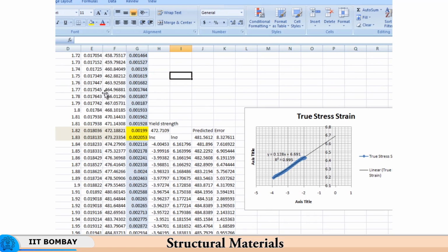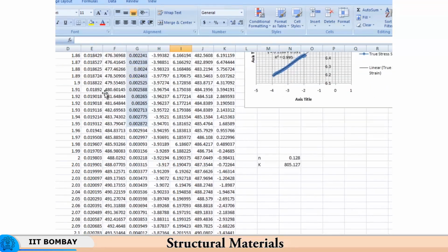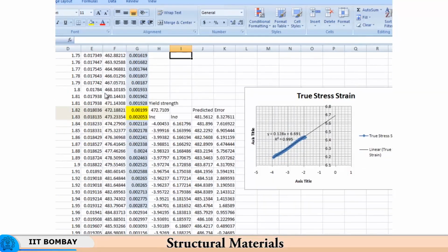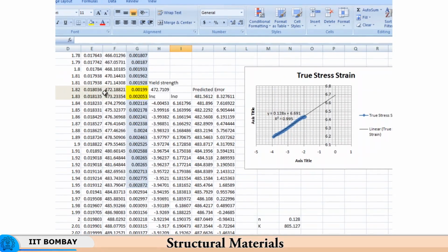So, I have R square always beyond 0.99. So, 0.995, 0.998 is good, and I get the value of n as 0.128 and k as 805.127. Now, based on this I recalculate the stress, because this stress is something I said is the yield stress, and from this point onwards the plastic strain would start coming into play. So, now I try to predict, using these values of n and k and the equation sigma equal to k epsilon to the power n, the stress values in the plastic regime.